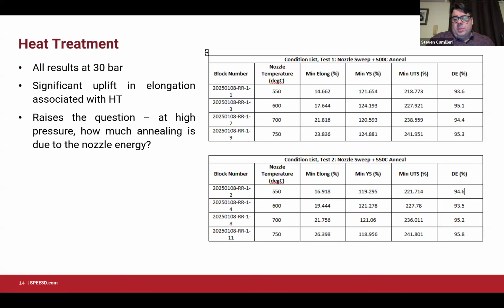At 30 bar, we would typically see maybe between 0.5 and 5% elongation. So fairly low elongation. But you'll notice in that min elong column, the third column along, the elongations are actually quite high, so 15 to sort of 28%. So just a very mild heat treatment is enough to recover ductility pretty substantially. You'll see that the yield stress has dropped as well, which is something we expect just with a bit of grain growth.